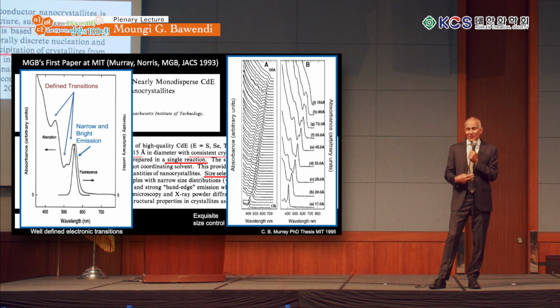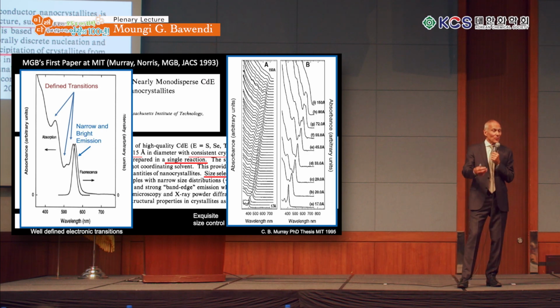And then I mentioned that to one of my colleagues in Germany, Horst Weller, who was working on quantum dots at the time. And I said, these are amazing, they're so bright. And he said, well, 15 to 20% means that 80 to 90% of your material is crap. And he was right. So that was also a motivation then to get this 15% quantum efficiency and try to make it as high as possible.